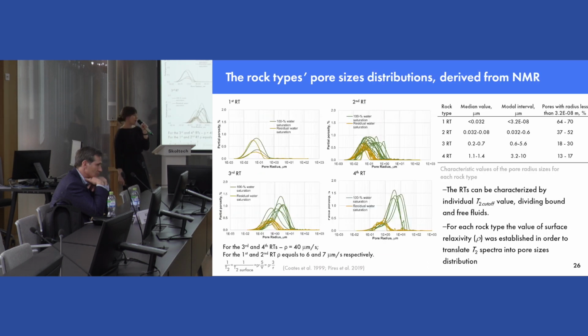Also in the study, for each unique rock type, I derived a T2 cutoff value from NMR, which divides free and bound fluids in the rock. And also I identified surface relaxivity, which is aimed at further translation of T2 spectra into pore size distribution. Also, it is worth mentioning that the best match of pore size distribution was obtained between NMR and combined CT and the capillary pressure curves pore sizes.